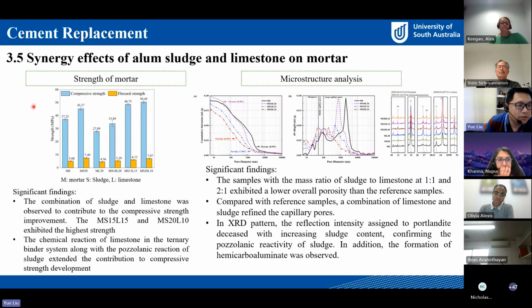And for the strength, the combined limestone and sludge can contribute to the strength development. This can be explained by the chemical reaction of limestone in the ternary binder system, along with the pozzolanic reaction of sludge, extending the contribution to the compressive strength development. For the porosity analysis, we can also see the combination of sludge and limestone shows a lower overall porosity than the reference sample, the pure OPC samples. And compared with the OPC samples, the combination of limestone and sludge actually refined the capillary pores.